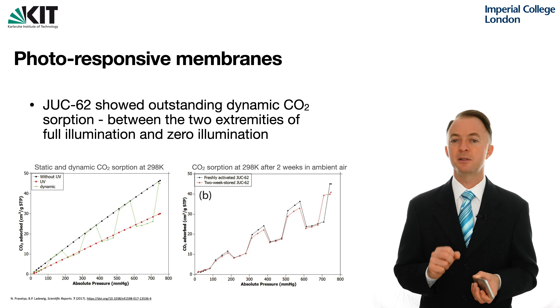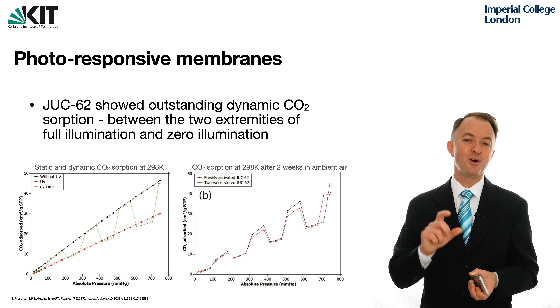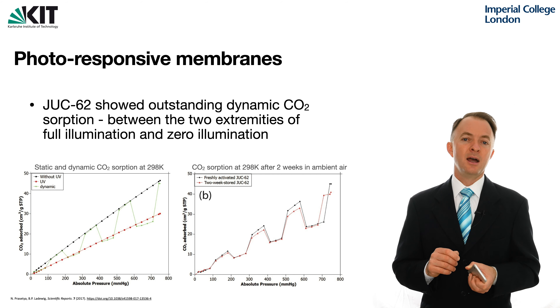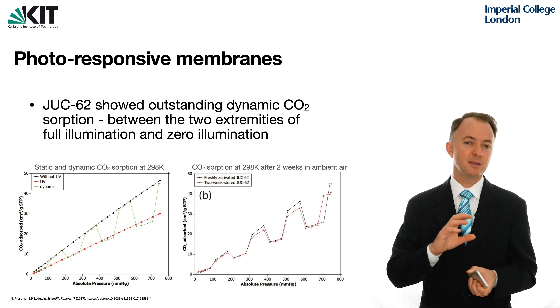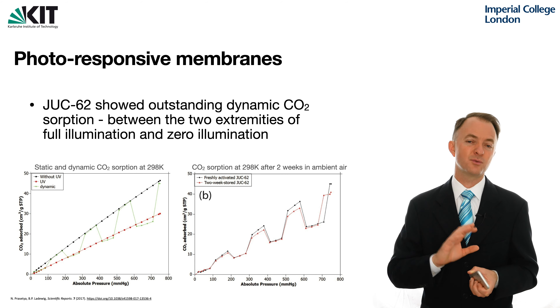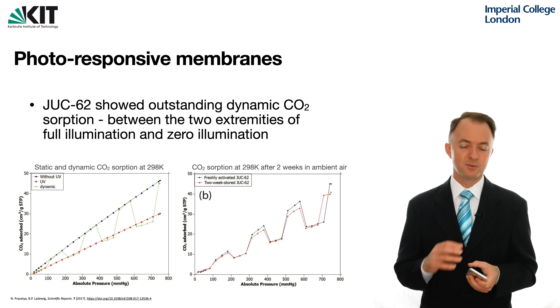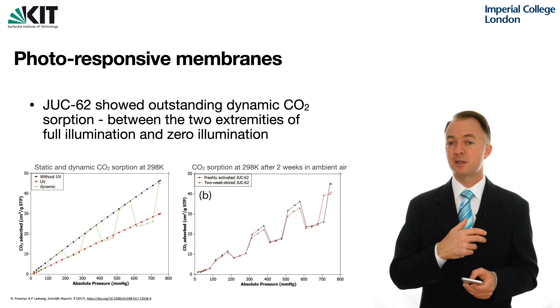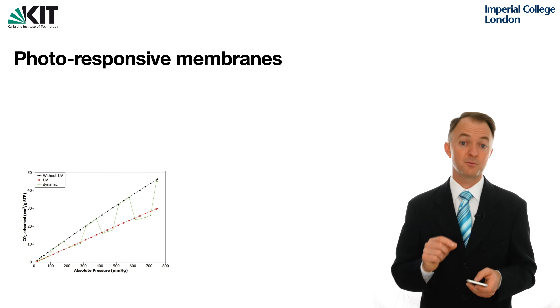The very short-term stability test result published in this paper — published in 2017 — was that if you synthesize the MOF and leave it on the bench for two weeks in ambient air with some humidity, then make the same dynamic photoresponsive measurement two weeks later, you get almost the same result. Powder XRD after storing it shows that it doesn't rapidly degrade. It's still not a monumentally stable material, but it's good and able to be produced into membranes, which was key for us. We wanted a relatively stable material that we can mix with a polymer and a solvent so that we can cast a membrane with our photoresponsive particles in there.